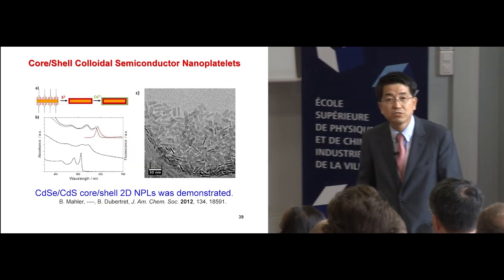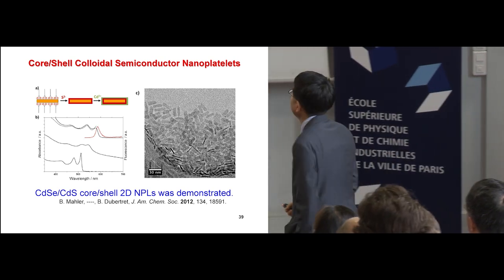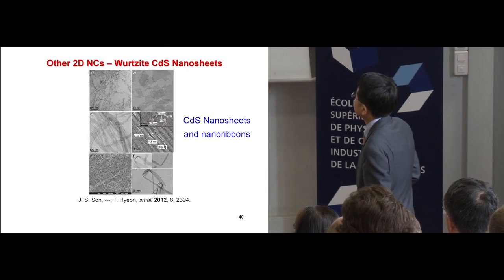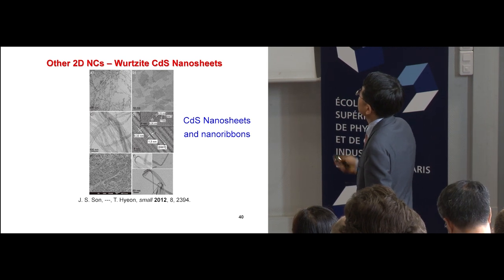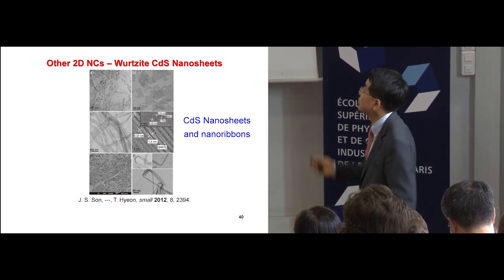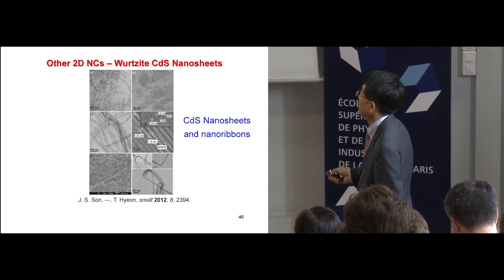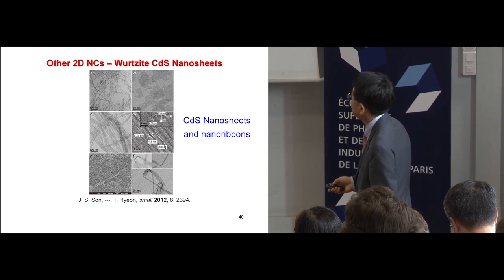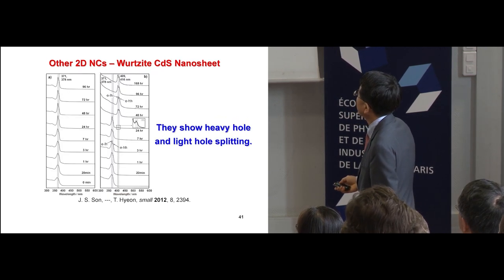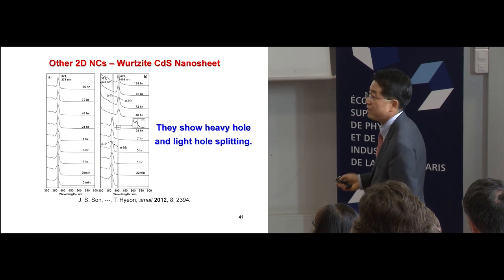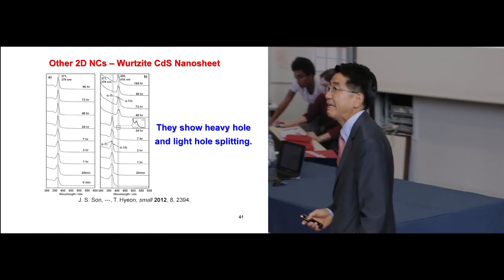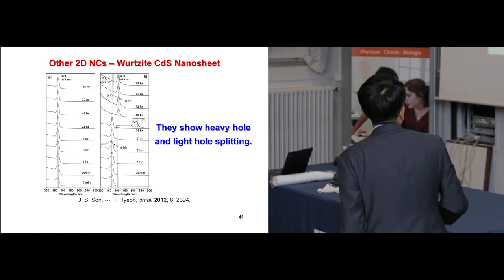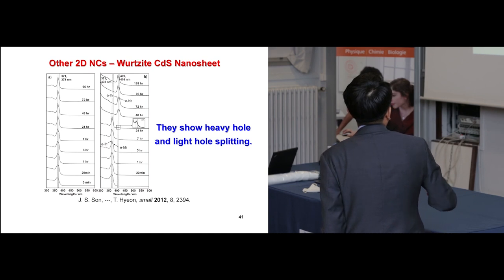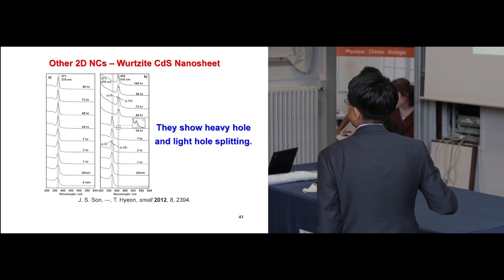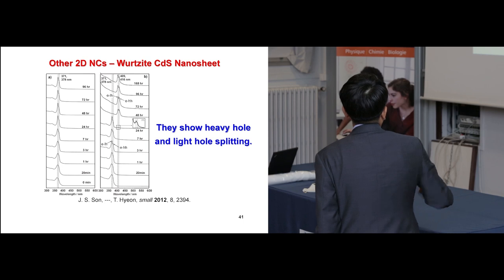So these two papers were published back to back. Core shell structures. And also, we could synthesize the CdS nanosheet, which we reported a couple of years ago in Small. This is not as dramatic as the CdSe case, but still, we could see splitting of the heavy or light hole subbands. We can see that over here.